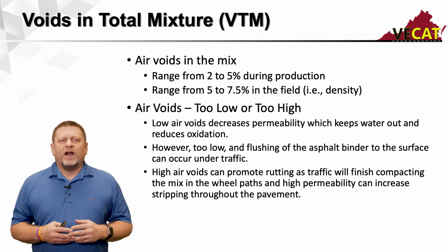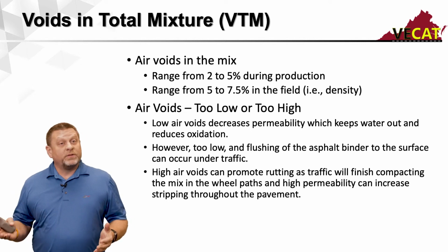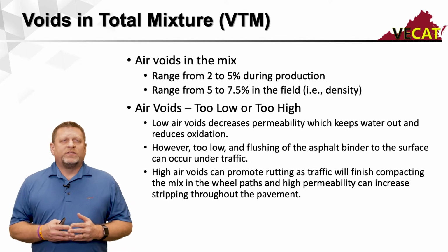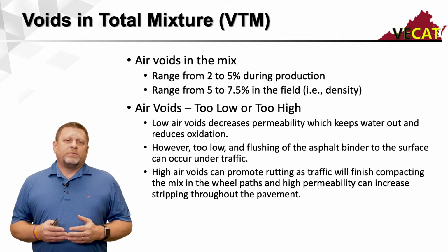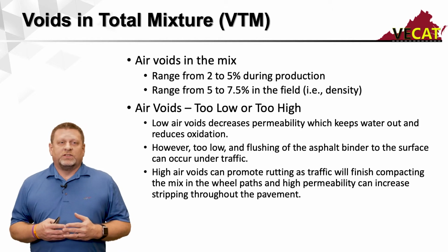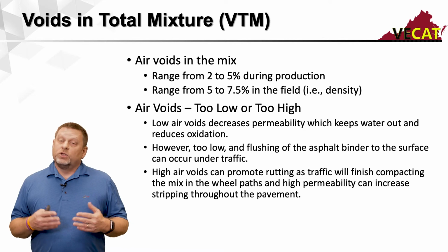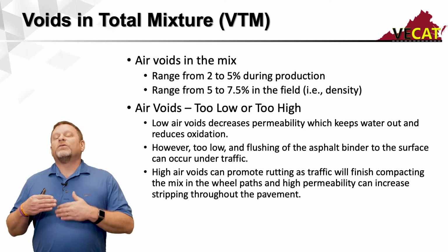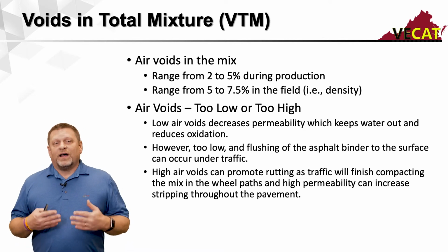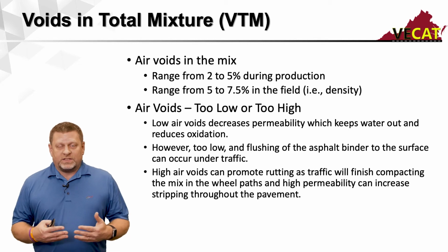But what happens if the air voids are too low or possibly too high? Low air voids decreases permeability, which keeps water out and helps reduce oxidation. So the tighter we can get the mix, usually the better, as long as we don't go too far. And a lot of it depends on how we're getting these voids as tight as we can.